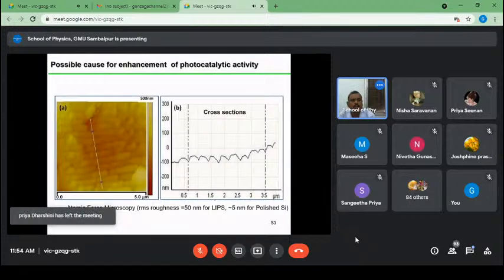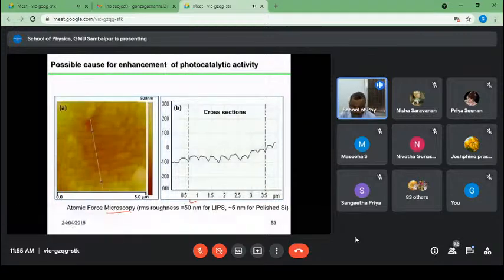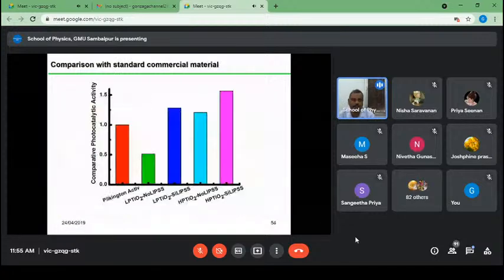Then the possible cause we have given here: we have done the AFM study, and we have found that the roughness has increased many times. So that has caused this photocatalysis enhancement, because the photocatalysis efficiency is much higher with nanoparticles or maybe larger surface area. So we have given this cause, and we have done some other studies that I am not going to describe to you. We have done this another study also.